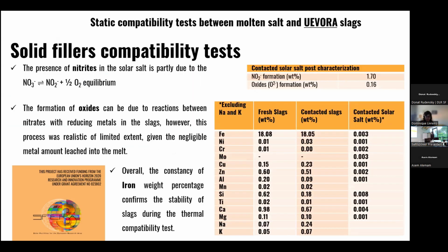The same experimental campaign was conducted with Evora slags. Also in this case, there is the presence of nitrites in the solar salt after the experimental campaign. Also in this case, there is the formation of the oxide, but it's more or less negligible. And overall, the consistency of the iron weight percentage before and after confirms the stability of the Evora slags during the thermal compatibility test.